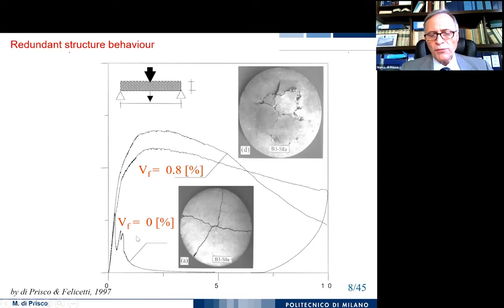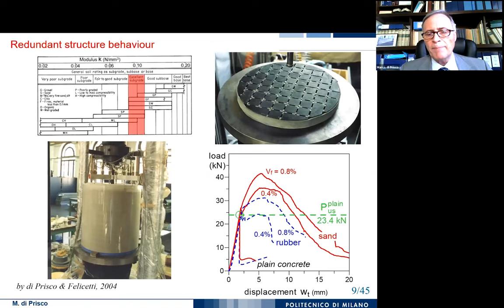of the structure. So if we have a plate which is supported on the perimeter, and it is a circular plate, and we load centrally, we will have a classical crack with the formation of two cracks along the diameter in a plain concrete, and a very brittle response. But if we pass to a fiber-reinforced concrete, we have a huge increase and also quite significant ductility of the behavior.